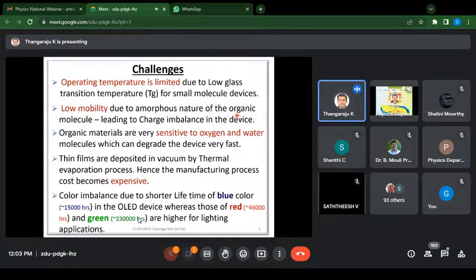And also these kinds of organic molecules are not periodically arranged. It doesn't allow the charge transportation from one end of the molecule to the other end, and it is just by a hopping process. Electrons are jumping from one molecule to another molecule, and that hinders the mobility of the organic molecules, leading to low charge mobility. And this low charge mobility is one of the issues to be addressed.